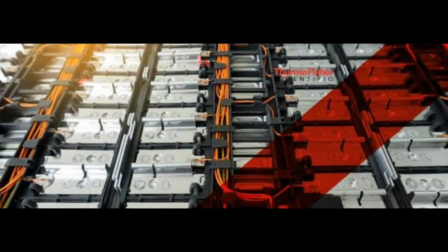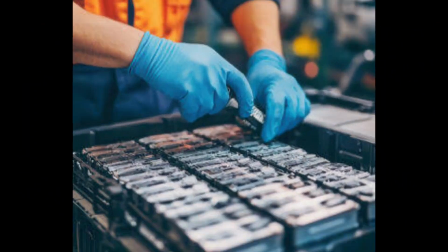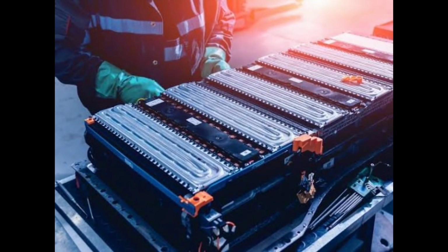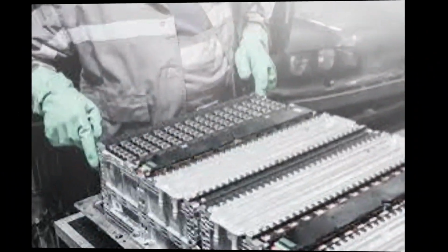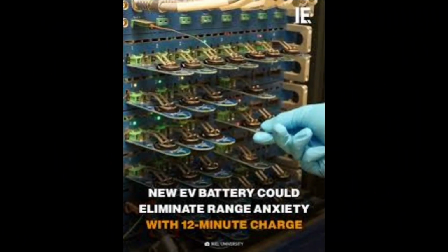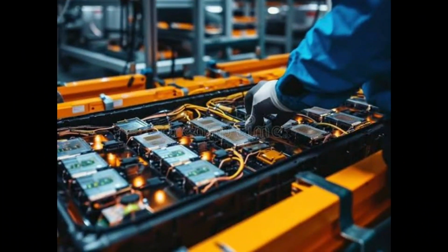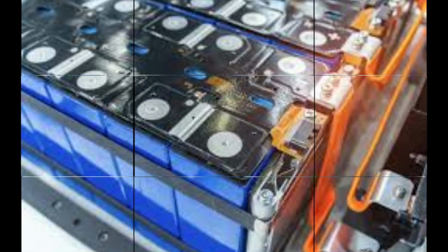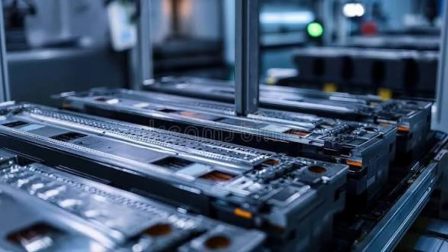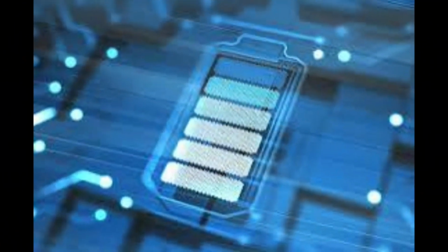The researchers used a rotational rheometer to simulate coating conditions with a thickness of 500 micrometers. The slurry contained lithium iron phosphate as the active material, acetylene black as the conductive additive, and a polymer binder dissolved in solvent. The team then dried the tested slurries into electrodes and assembled them into battery cells for further performance analysis. Microscopy studies confirmed that intermediate shear conditions created the most balanced conductive structure.